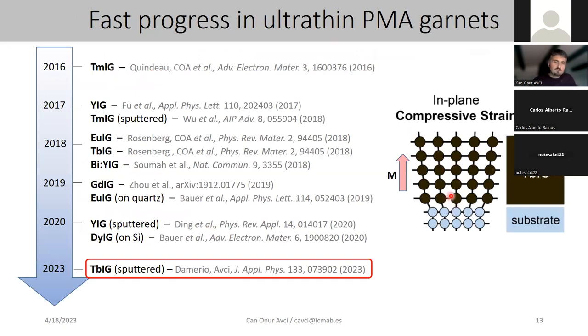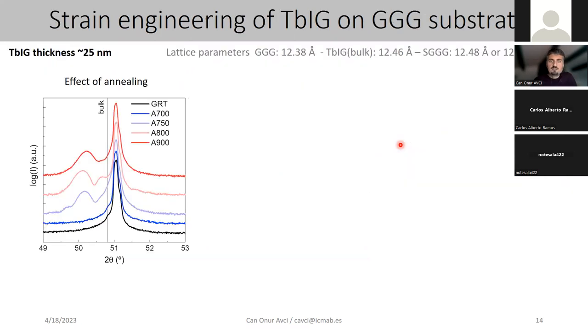So in the case of terbium iron garnets, for instance, you grow them on a typical GGG substrate, so gadolinium gallium garnet, and because of the lattice mismatch, you get some strain. So this compressive strain in terbium iron garnet drives the magnetization from in plane to out of plane, so that the film gets perpendicularly magnetized. And this is basically something that you can easily engineer in the films.